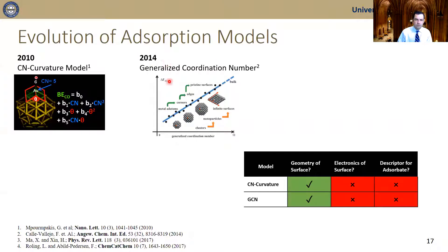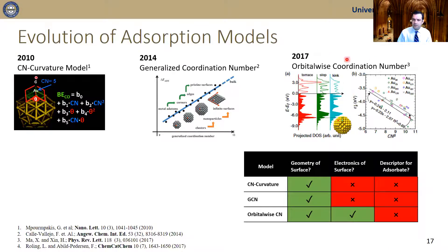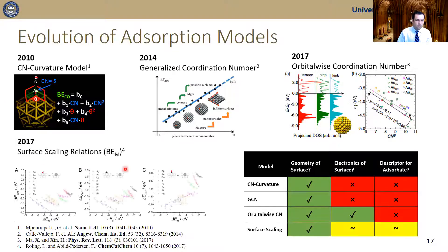After that, Professor Philippe Sautet in 2014 introduced the generalized coordination numbers, which — in addition to the coordination number of the site — take into consideration the coordination numbers of the second neighbors. In 2017, Professor Hongliang Xin from Virginia Tech introduced orbital-wise coordination numbers, which additionally take into consideration the electronic structure of the surface. Also in 2017, Röling and Abild-Pedersen introduced surface scaling relations, demonstrating that the binding energy of an adsorbate is correlated to the binding energy of the metal site on your catalyst.